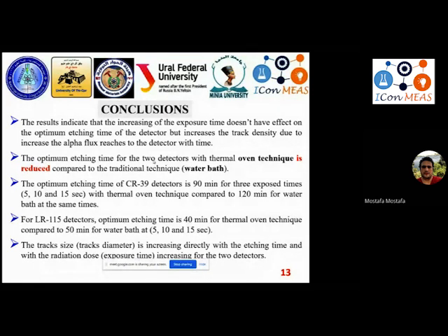Secondly, the optimum etching time for the two detectors with the thermal oven technique is reduced compared to the traditional technique, like the water bath. The optimum etching time of the CR39 detector is 90 minutes for the 3 exposure times, 5, 10, and 15 seconds with the thermal oven, compared to 120 for the water bath. For LR, 40 minutes for the oven technique compared to 50 minutes for the water bath technique. The track density and track diameter increase directly with the etching time and with the radiation exposure time for the two detectors.